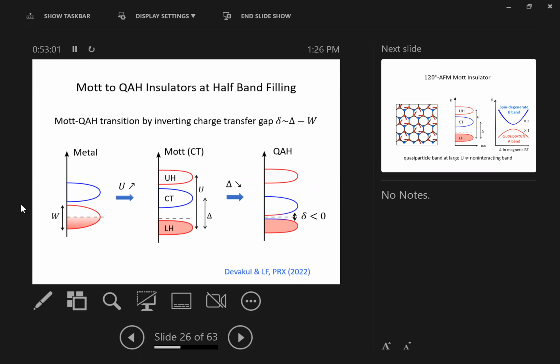So first, in the absence of interactions, we are dealing with a half band filling, so the system is necessarily a metal. But once I include the Hubbard U, I can split this into a lower and upper Hubbard band, so the system can be an insulator. But the system consists of 2 layers. The Mott insulating gap U is large. The second layer states are actually near the Fermi level. It's a charge transfer band, right?